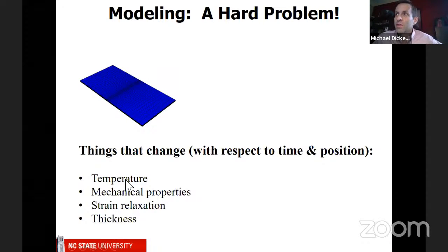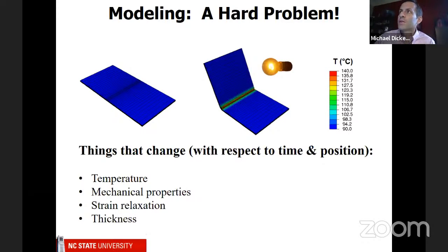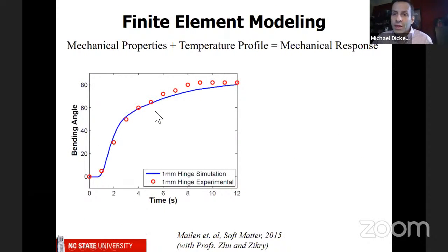First of all, the temperature as a function of time and position. So if you pick any one of these points, the temperature is going to be changing pretty much at any given time. Since the temperature is changing, the mechanical properties change. Remember also, as you heat it, it can shrink. And so that's also changing, which is changing the shape. And then if it shrinks, it also changes the thickness. So this is a really good problem for what's called finite element modeling, where you break up your material into little small pieces and you model physically what happens to each one of those little things and how they interact with each other. And so this is kind of what it looks like in the model. I'm not going into a lot of details, but in the end, we were able to model the angle quite a bit better than just using simple geometry.